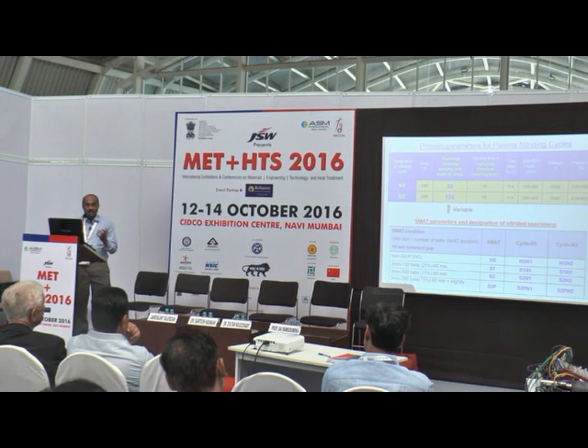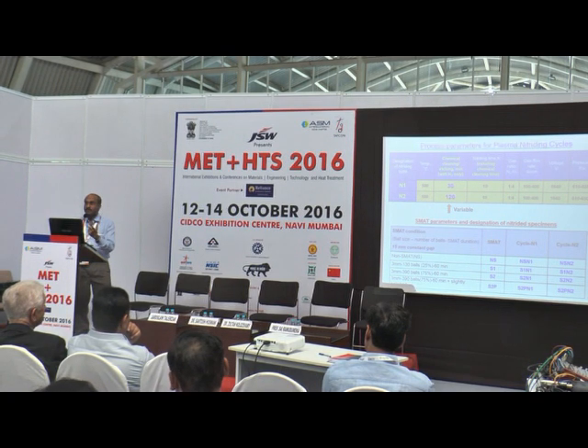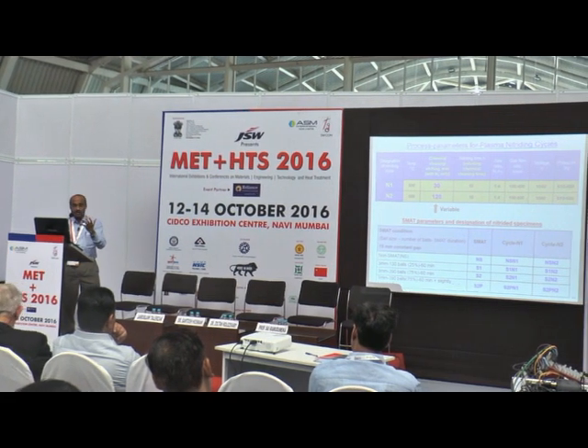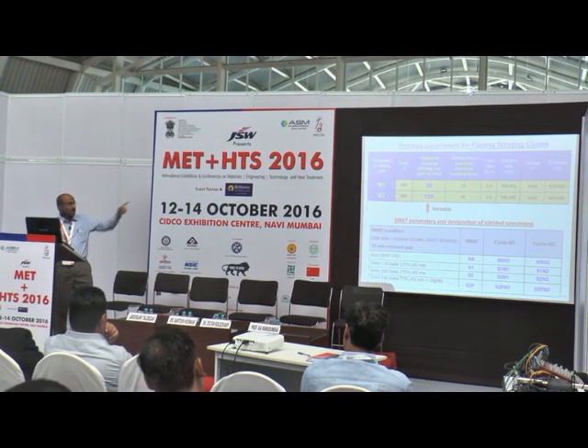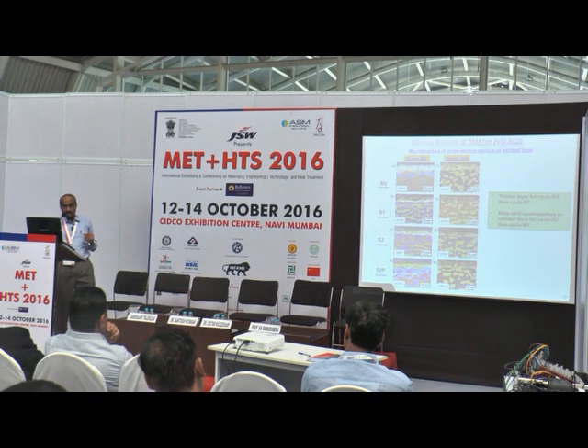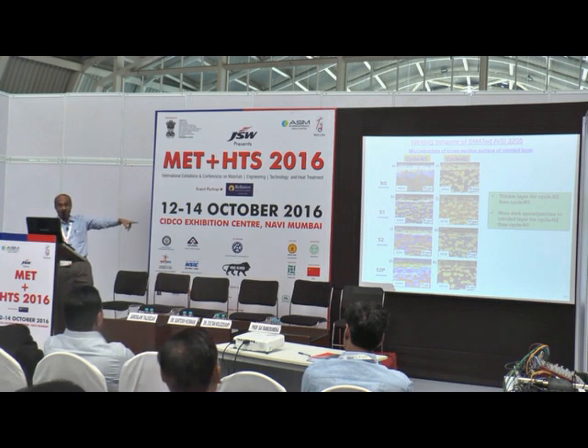How do I prove that? Intentionally, we selected 2 sets of experiments. In one experiment we selected a lower sputter clean duration, and in the other case a higher sputter clean duration, that is 30 minutes and 120 minutes. What is the effect of that? This set of experiments is N1, that is the lower sputter clean duration, and the other is the higher sputter clean duration.